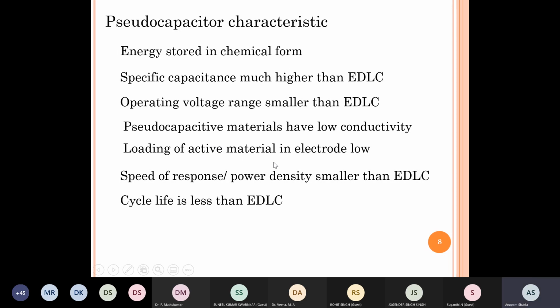Loading of the active material in the electrode is low. For example, the electrode is never a pure active material. It also requires some conductivity additives and other additives for the electrode to be mechanically strong and for other properties. So the net amount of energy stored per unit weight of electrode becomes even lower if the proportion of active material holding the charge is lower. And because the response of formation of the electric double layer is very fast compared to the speed of reaction.